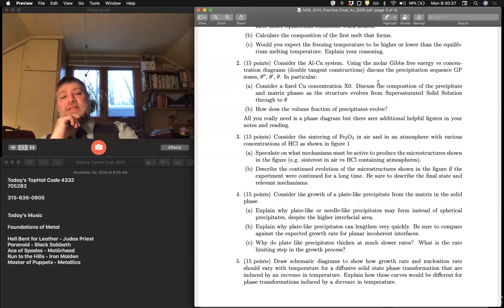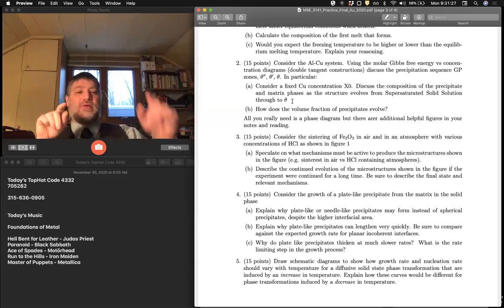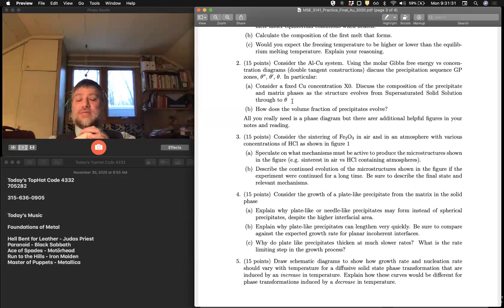And then as you go through it, what are the compositions of the precipitate and matrix phases, right? So remember that the GP zones are essentially clusters of copper atoms. So the GP zones are much higher in copper than the other precipitates, right? And then theta double prime is a stoichiometric compound that's lower in copper than the GP zones, right? So if I keep the same amount of copper in the precipitates, what has to happen to my volume fraction as I go up, right? The precipitates become leaner in copper, so there has to be more of them, right? And if we look at where the intersections in our common tangent is, it means that our matrix is also getting leaner in copper.